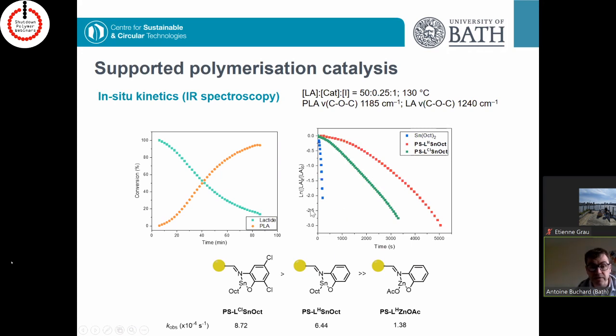However, our rates are not ridiculous at all. And you can see here in green, we've got our fastest catalyst, which is this supported tin octanoate catalyst based on those chloro ligands, followed by the hydrogen version, let's say, in red here. So we're quite happy with this.